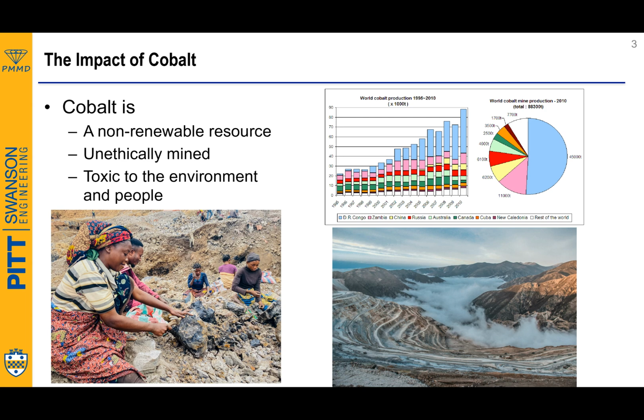However, there are compelling reasons to replace cobalt as a binder for cemented tungsten carbides. Cobalt poses significant health risks as prolonged exposure can lead to respiratory issues and other serious health problems. Additionally, cobalt is relatively expensive, toxic to the environment, and surrounded with human rights issues. By exploring alternative binders, such as iron or nickel-based alloys, we can enhance the safety, sustainability, and cost-effectiveness of cemented tungsten carbides while maintaining their superior performance characteristics.